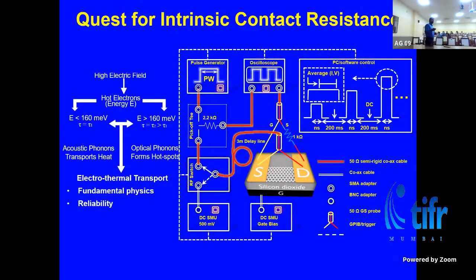Now, this was a separate work which we published in APL a couple of years back. This is a setup that we built to measure transport at nanosecond time scales. We measure down to 2 nanoseconds. The idea was to measure carrier transport at time scales that are shorter than the thermodynamic time, so we don't want the system to heat up, and we still want to measure current.